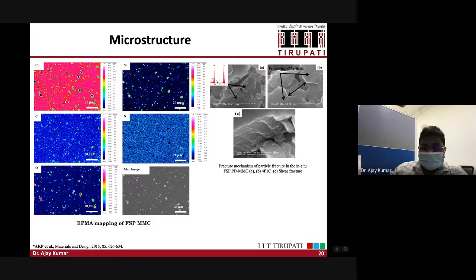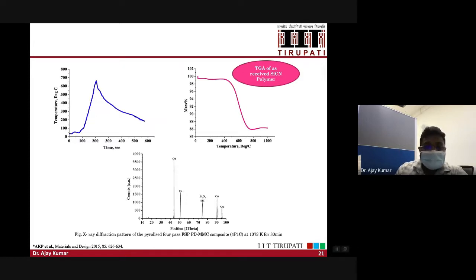So as you know, during the FSP process, the tool rotates at high RPM, and due to the lot of shear forces generated during the process, those particles will be fractured. So you can see the shear fracture on these particle surfaces and detachment. And these particles will keep on fracturing until they reach a critical size. Okay. We have also confirmed the transformation of the polymer phase to the ceramic phase. And the ceramic phases we have got are Si3N4 and Si from the X-ray analysis.